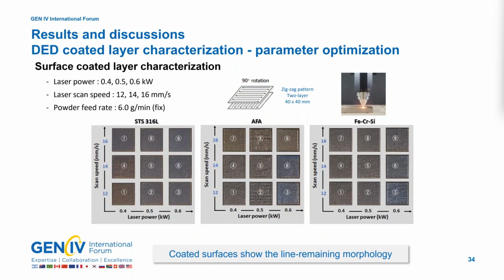The variables used for parameter optimization were also applied to the surface coating. The deposition was performed using a zigzag pattern with 2 layers rotated 90 degrees. Visually, the coated surface shows a line-remaining morphology.